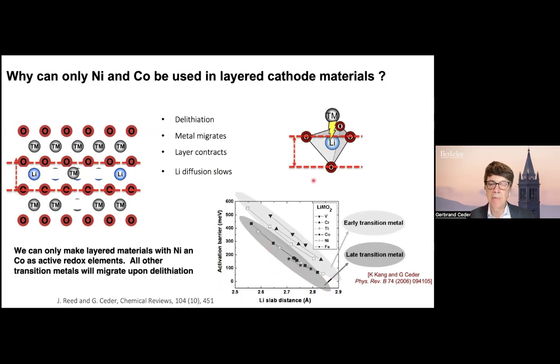And the reason is actually fundamental, related to the crystal structure of these materials. These materials are close-packed oxides, meaning that the oxygens are essentially stacked FCC with some distortion. And in any close-packed oxide, to move from one octahedral site to another octahedral site, you have to migrate through a tetrahedral site. So the octahedral site's face is shared with this tetrahedral site. And when lithium migrates through there, it is in close contact with the transition metal. And this electrostatic interaction, this close electrostatic repulsion, is what sets the activation energy for lithium hopping.